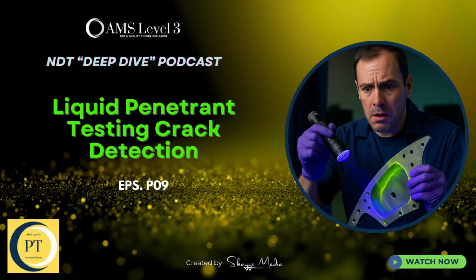And there's a flip side too, isn't there? A danger in trying to clean too aggressively, especially with mechanical methods? Oh, definitely. Big hazard. Using things like grinders, abrasive blasting, or even peening can inadvertently smear the metal surface. Or it can cold work it. Smear it. Yeah, it basically pushes or flows the surface metal, physically closing off the opening of an existing crack or discontinuity. If that smeared layer is there, the penetrant can't get in, and you'll completely miss the flaw. That's a huge risk. You could sign off on a bad part just because you cleaned it the wrong way. It happens. And if that surface gets smeared, sometimes the only fix is to use chemical removal, like etching or pickling, just to get rid of that damaged layer and make the test reliable again.